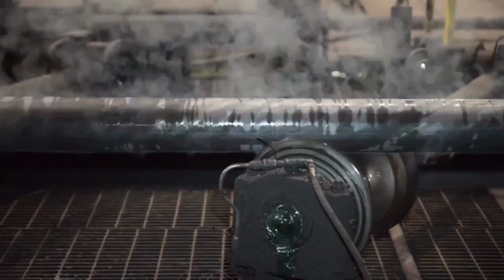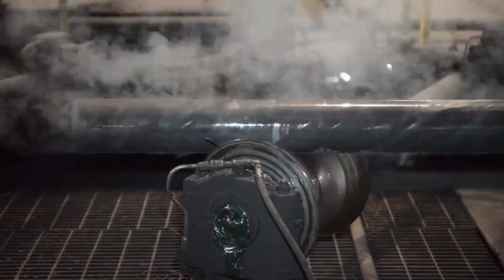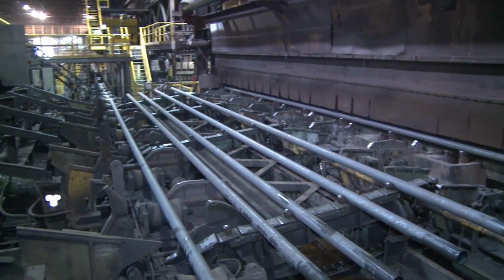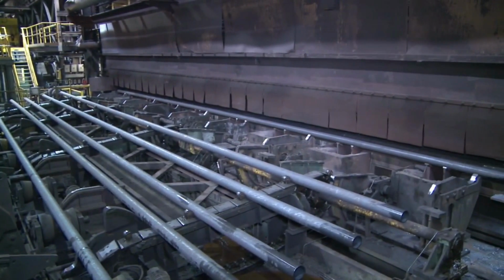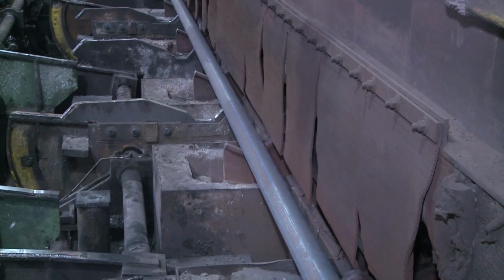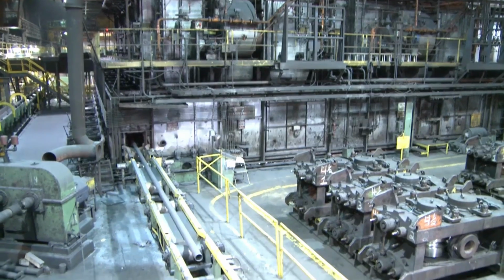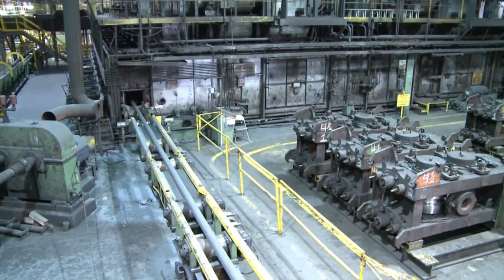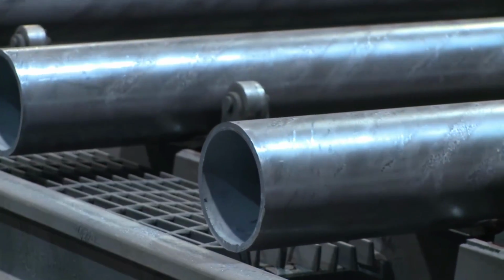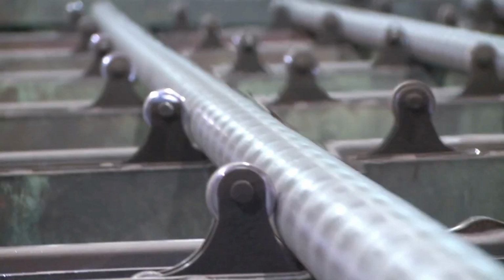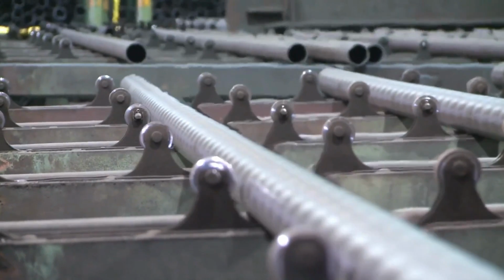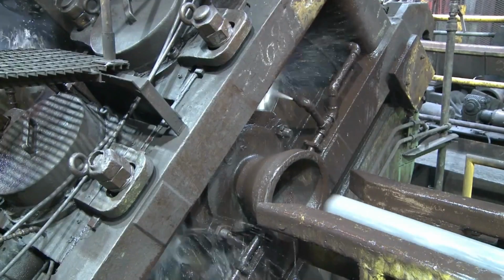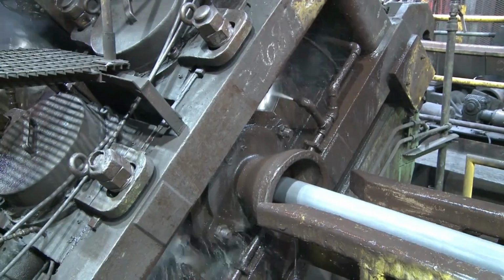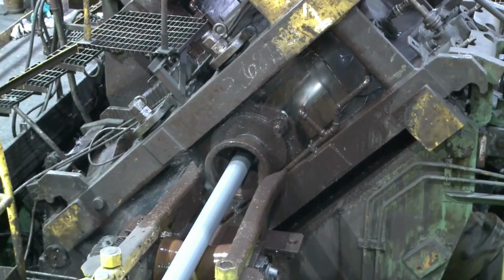The pipe is now transferred to a tempering furnace where it will be preheated to 510 degrees Celsius, then slowly cooled. This tempering process increases the pipe's ductility or toughness. Precise control of time and temperature during the tempering process are critical to achieve well-balanced mechanical properties in the finished pipe. After quenching and tempering, the pipe passes through a 3-stand resizing mill which calibrates the outside diameter to final